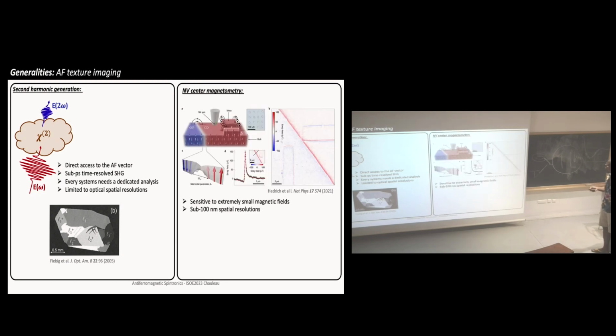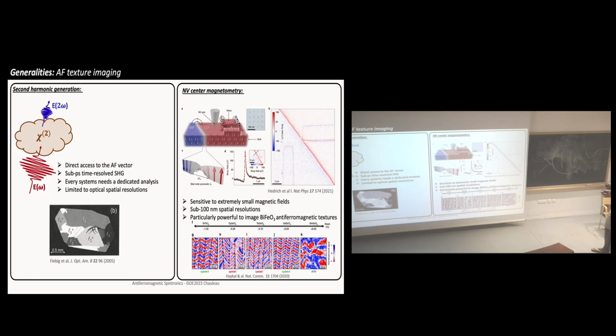The second technique, which Karim just introduced before, is NV center magnetometry. Here, you don't directly access the antiferromagnetic vector, but since you can sense extremely small magnetic fields, you can have access to some extent to what's happening, for example, at domain walls of antiferromagnets, or if there is a step. So you have to be careful, but you can get some information on antiferromagnetic materials with NV magnetometry, and actually it has been extremely powerful to study the antiferromagnetic texture in BFO, where associated to the antiferromagnetic texture you have a tiny spin density wave which produces this magnetic field.